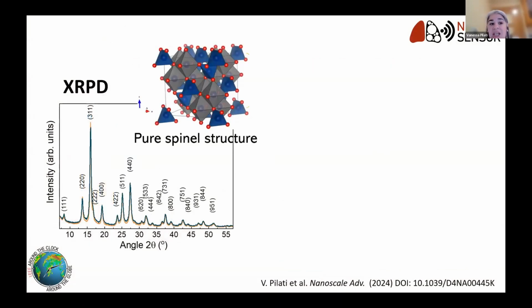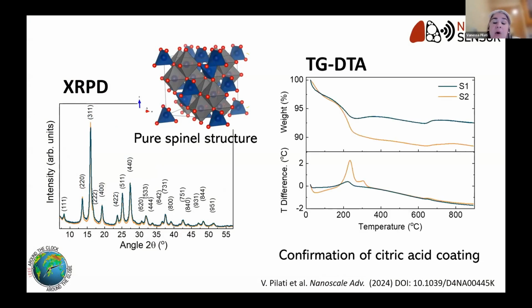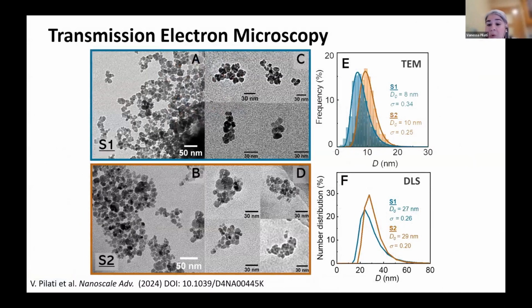We made some characterization with X-ray powder diffraction. We saw that they are pure spinel structure, which is good. We confirmed the citric acid coating by thermogravimetric analysis. We synthesized two different samples with different diameters to investigate the influence of the size in the magnetic detection. And they present a log normal size distribution.